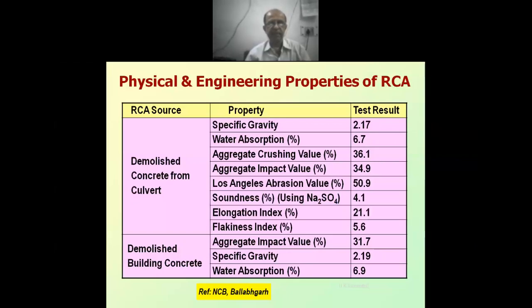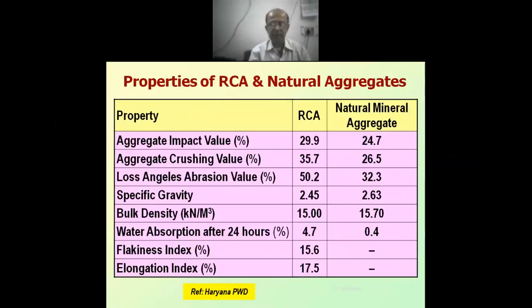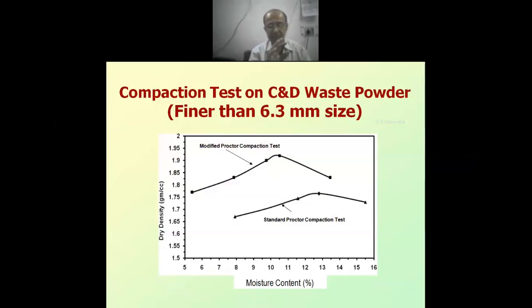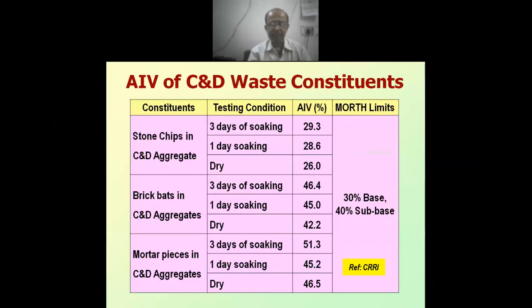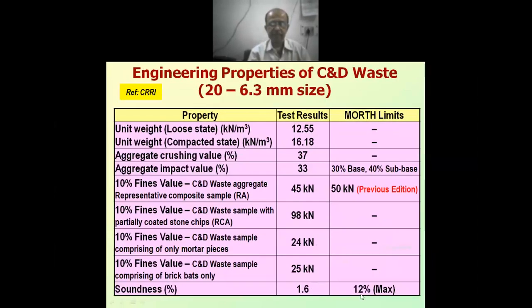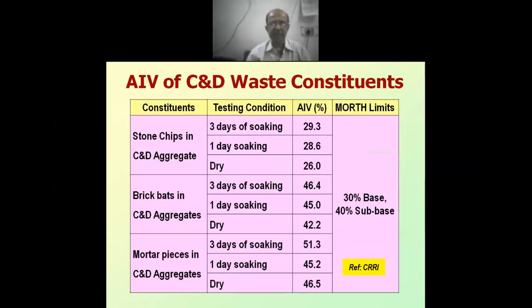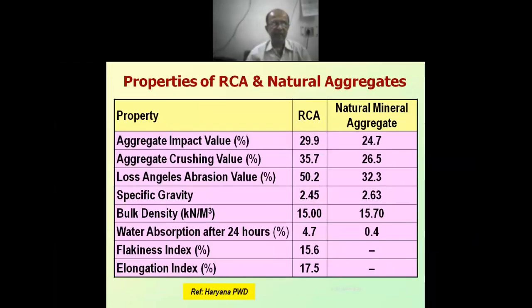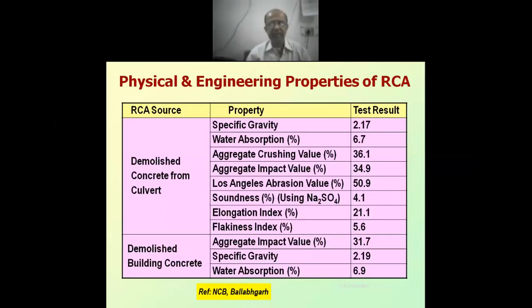Aggregate crushing value around 36%, impact value around 35%, Los Angeles abrasion value around 51%, soundness once again okay, 4.1% with sodium sulfate. It's sodium sulfate and magnesium sulfate, sorry, not calcium. Sodium sulfate and magnesium sulfate, so Na2SO4 and MgSO4. I stand corrected. This 4.1% is lesser than the 12% that MORTH has specified. Whether you use Na2SO4 or MgSO4, the 12% is the same. Elongation index and flakiness index are well within the limits.